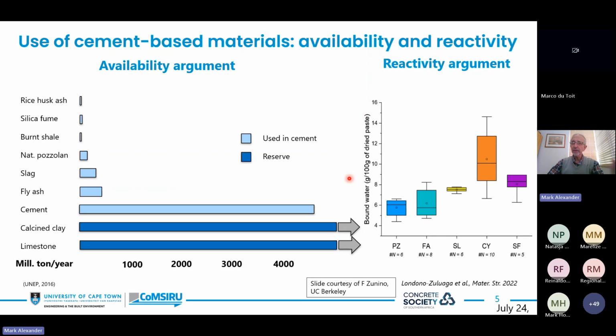Also on the reactivity side, if you look here, you see that, let's say, fly ash, a typical material that we use, with this bound water here at gram per 100 grams of the paste, sits here at around about 5 of those units. Natural pozzolans, similar. Slag, about double that. And then the clays. The clays, as you can see here, are really superb materials. They have double the reactivity of, for example, fly ash, and even better than silica fume. So these are materials that really deserve our attention.